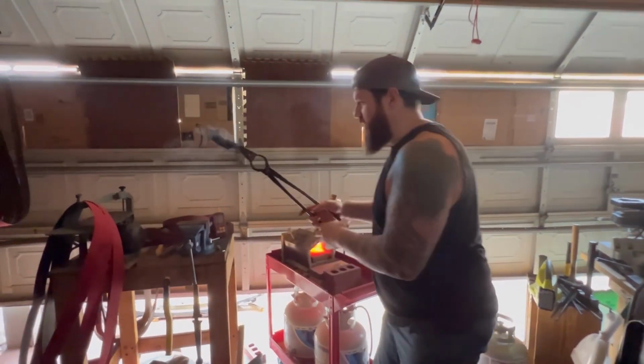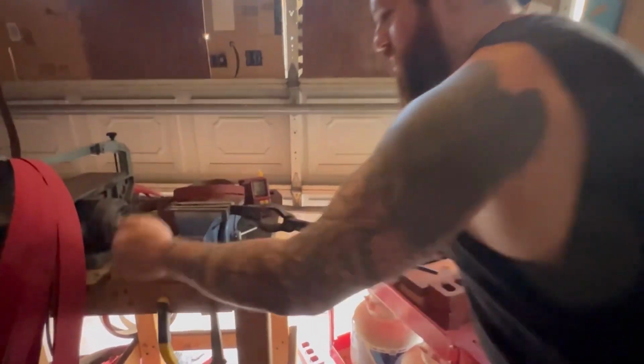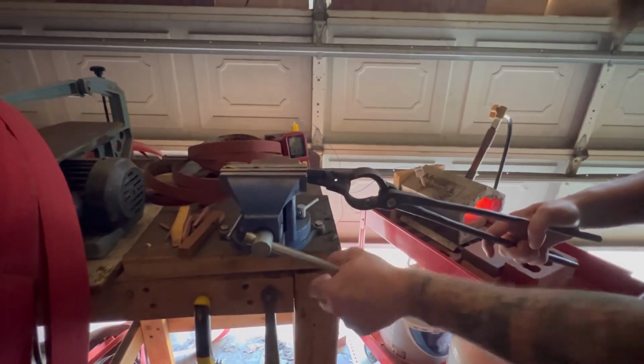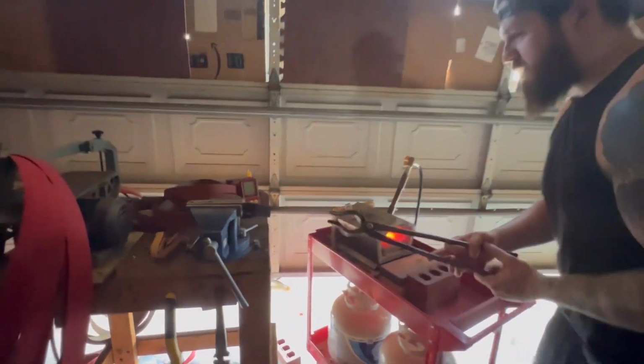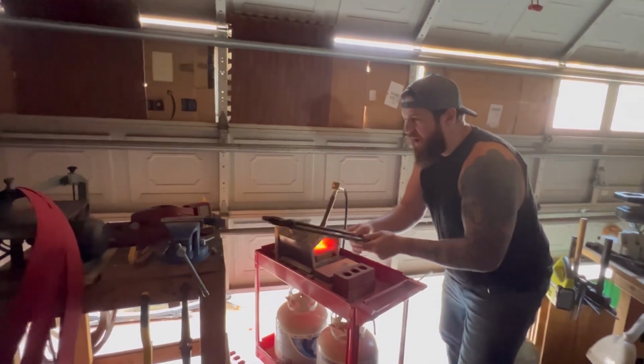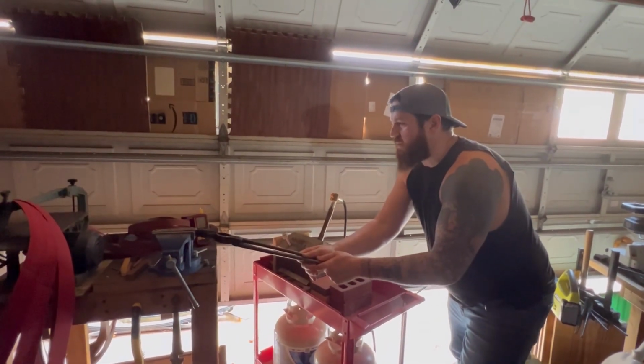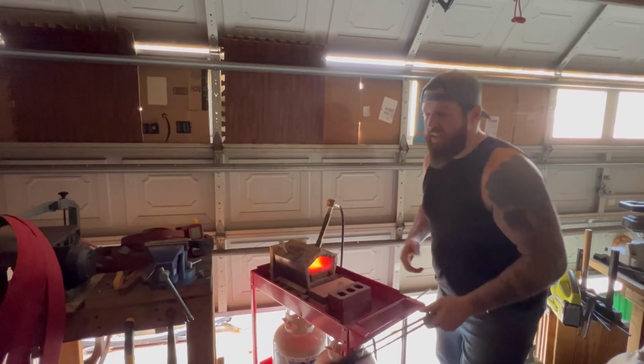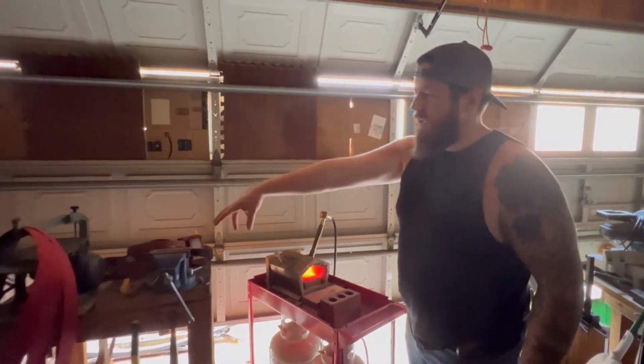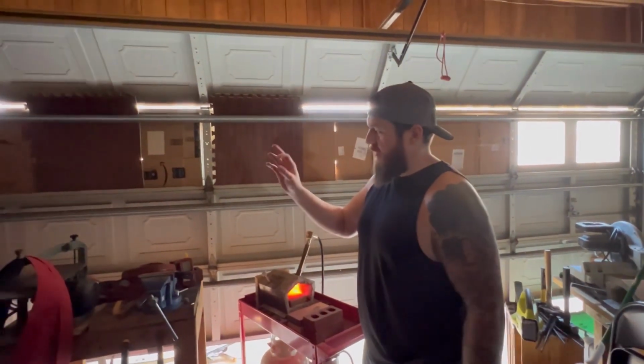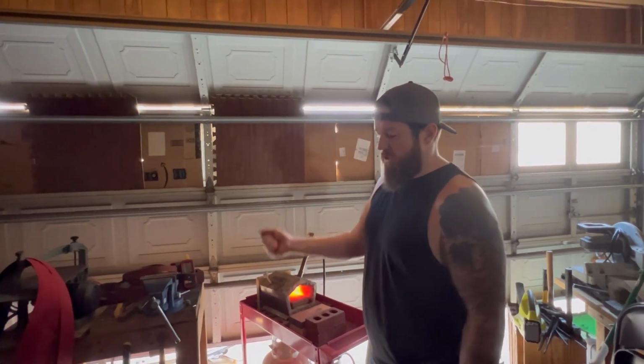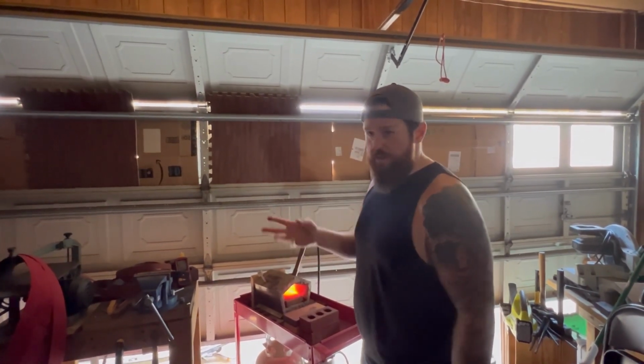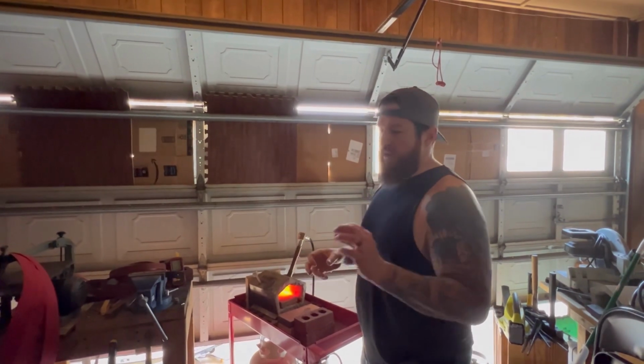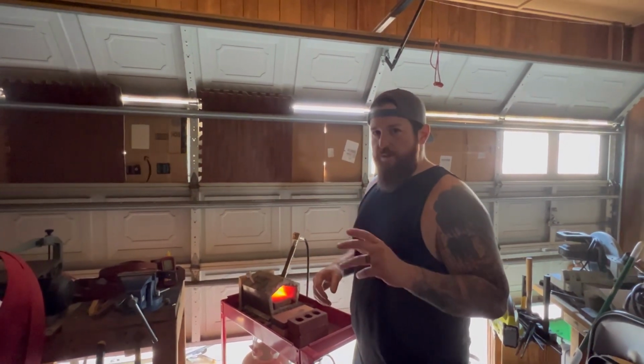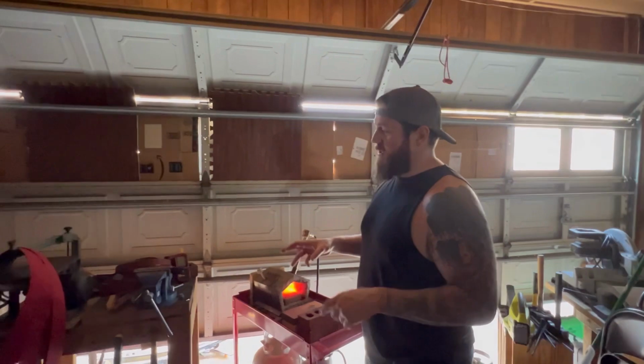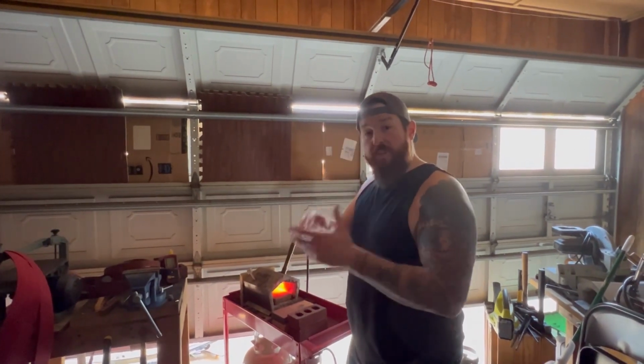All right, last thing I do here, stick it in the vise just to make sure it stays straight as it cools. You have a few seconds sometimes if you get a little bit of a warp to straighten that warp out. Otherwise, you might break it. When you harden it, it's at its most brittle. So once it's done cooling off here, and I can touch it by hand, it's going to go in the oven for 4 hours. The tempering process brings that hardness down just 1 or 2 steps, so that it holds a good edge, but it also isn't brittle.